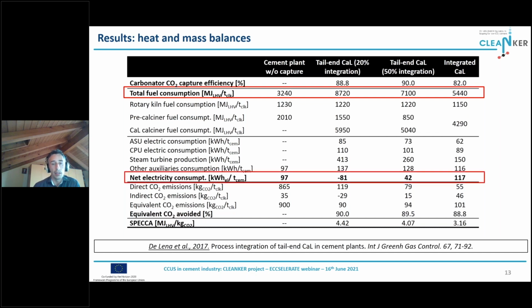On the other hand, the higher the fuel consumption, the higher the thermal input, and the higher the electricity that we can produce by recovering the heat from the CO2 capture system. As you can see, for instance, in the first tail end case with 20% integration, we have an export of electricity. As for the equivalent CO2 avoided, we can see that all the systems approach 90% of CO2 avoided. And as far as the SPECCA is concerned, the best value is given by the integrated calcium looping.